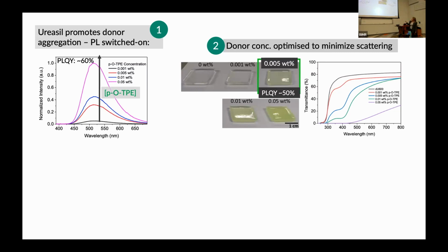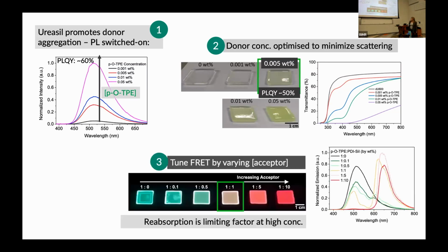So we settle with a concentration of around 0.005 weight%. We then optimize our FRET efficiency by tuning the donor to acceptor ratio. And you can see as we increase the acceptor concentration, we essentially get a change in the emission color. But we have a problem because when we get to really high acceptor concentrations, we do start to get reabsorption problems associated with the acceptor because it overlaps with its own emission spectrum. So you get reabsorption issues there.